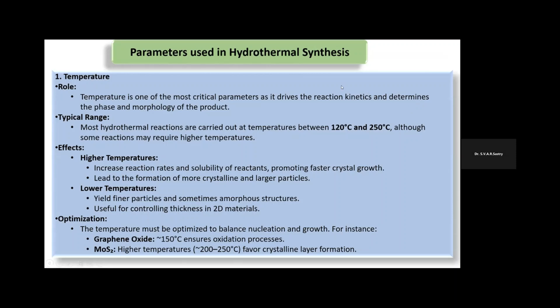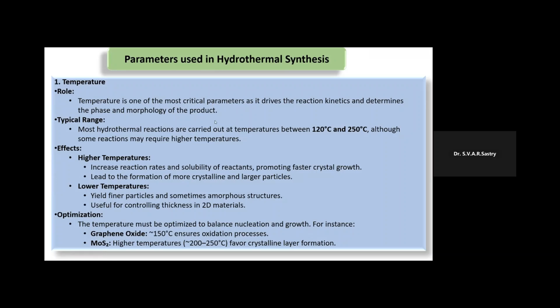So what are the parameters used to control the hydrothermal synthesis method? The first and most important parameter is temperature. We see that temperature is one of the most critical parameters. It drives the kinetics of the reaction and determines the phase and morphology of the product formed. The typical range of temperature is between 120 to 250 degrees Celsius, although some nanoparticle synthesis may require